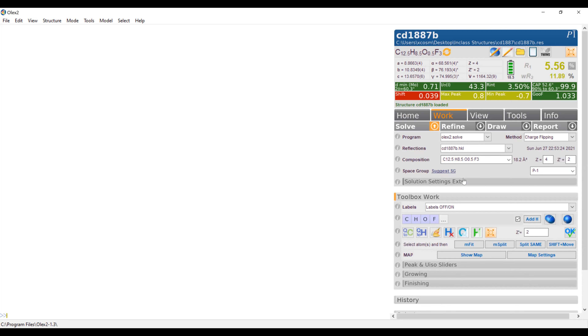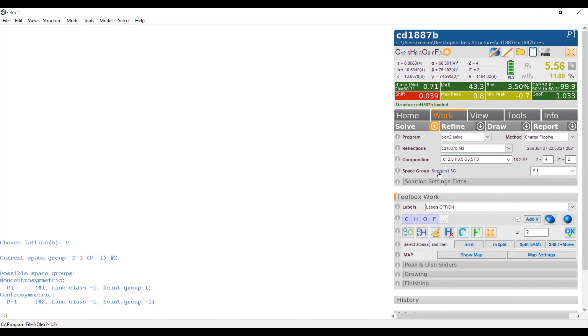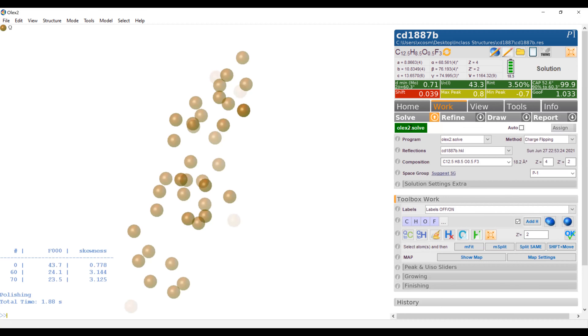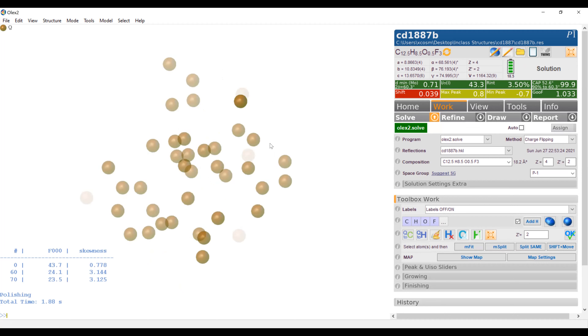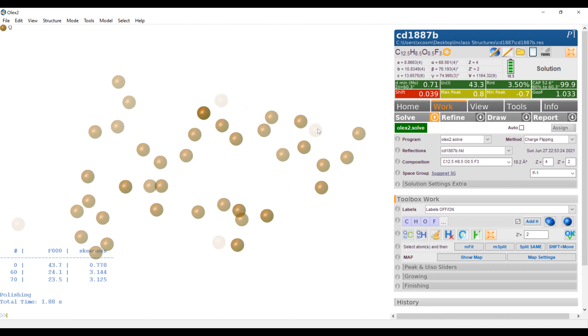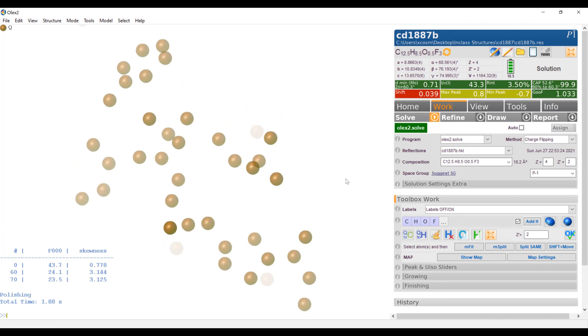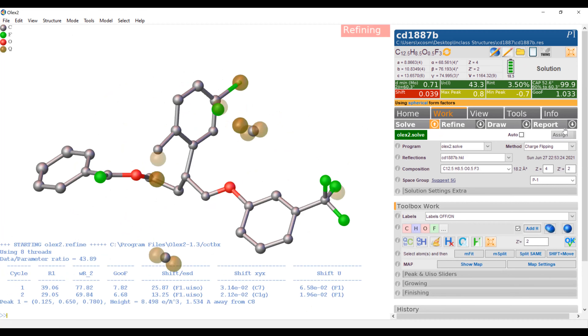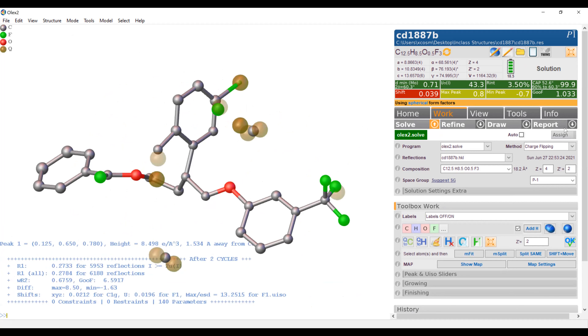I'm using OLEX2.solve with space group P1-bar. If you want to look for a different space group, you can go to 'suggest space group' — and it still suggests P1-bar. So let's go ahead and hit solve. The solving is done and it gives us some electron density plot of this crystal structure. Then we're going to click 'assign' and it's going to label or identify some of the atom types based on the chemical formula we've given it.